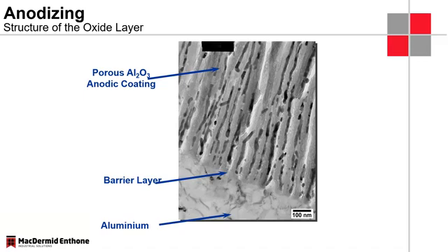So here again, this is another cross-section of an anodized surface, and we see quite nicely at the top of the picture the aluminum oxide layer. We see all those little channels, these little capillaries that run all the way down to the barrier layer, and this is really the interface where the aluminum oxide layer grows. And then just right underneath this barrier layer, we have the aluminum substrate.